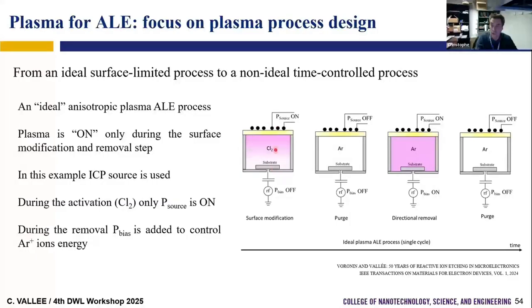So we do a chlorine plasma, or you can flow chlorine gas, but usually we do chlorine plasma. Then we have a third step. So we have no more plasma, just to remove the chlorine. And then we have the argon plasma to bombard with ions to remove the modified layer. And then we have, this is the removal step, what we call a directional removal. So it's a directional plasma ALE. And after we have the purge to remove, and then you repeat. So this is what we do.